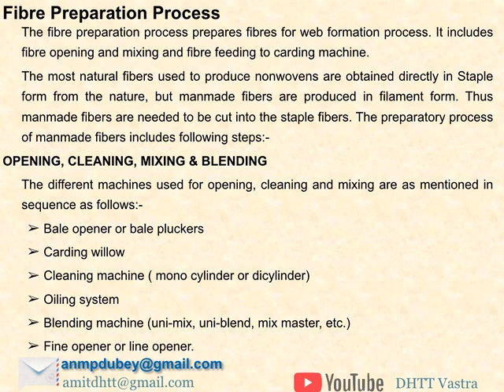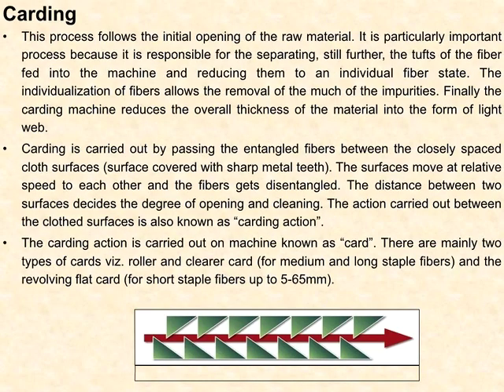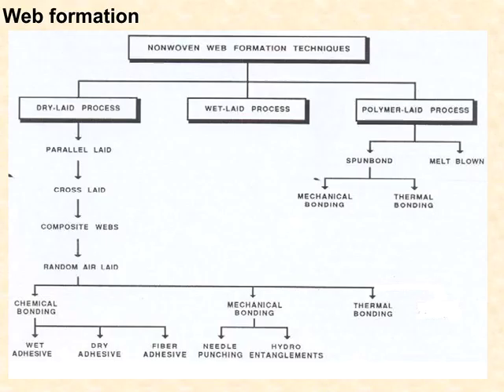The distance between the two surfaces decides the degree of opening and cleaning. The carding action is carried out by the machine known as a card. There are mainly two types: roller and clearer card, used for medium and long staple fibers, and revolving flat card, used for short staple fibers.